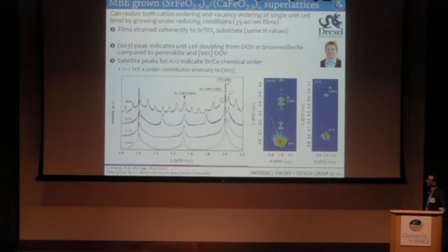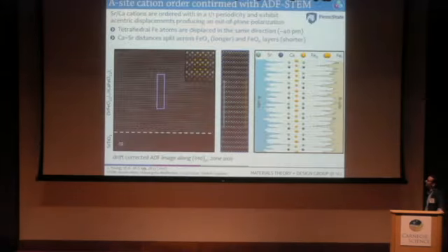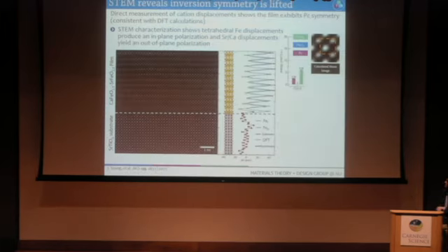And so then what we did is we went to the group of Nassim Alem at Penn State to look in real space, is there chemical order? This is annular dark field STEM imaging in a very large field of view of this crystal of strontium ferrite, calcium ferrite. This is the 1,1 period superlattice. And you can indeed see that there is A-site chemical order shown in this projection, so taking slices along this direction. The other thing they looked at is they mapped out locally displacements of both the iron and the A-site cations, strontium and calcium, and fit those displacements to our density functional theory predicted structures and find very good agreement.